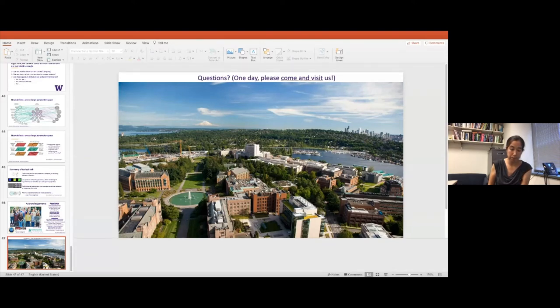All right. Peter wants to know, could you comment on the requirements to the purity of the materials, both in terms of impurities and in terms of other not useful defects? Are there limits on their concentrations? Yeah, so because almost always you're storing the information in a spin state, the bad impurities are ones that have an unpaired spin. These can be nuclear or they can be electronic. If you have a nearby electronic spin, you can calculate what the dipolar coupling is of the nearby spin. And if it's frozen out, that's great. If you can go to low enough temperature so it's static, that will help quite a bit. I would say to do this kind of coherent manipulation, you definitely want things below parts per million to start with.